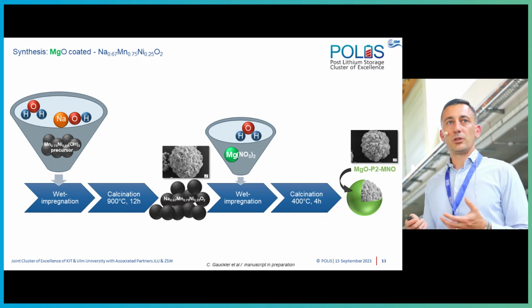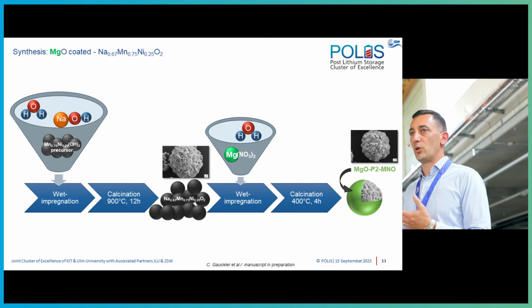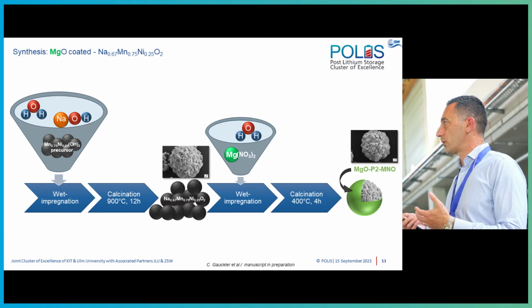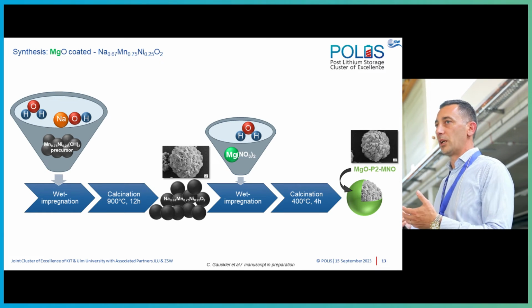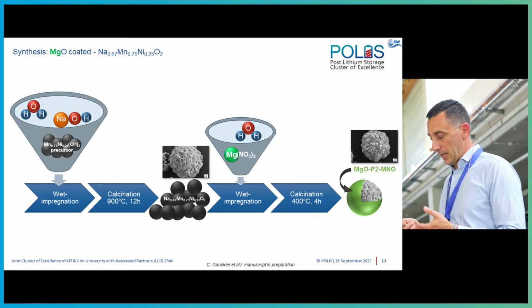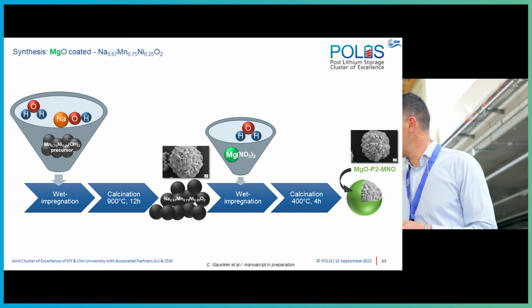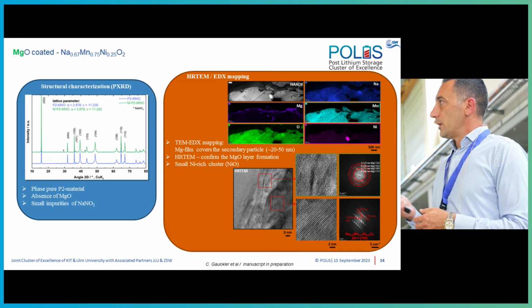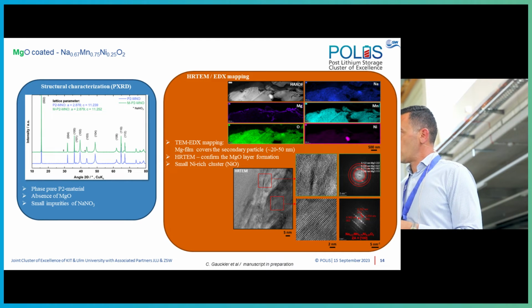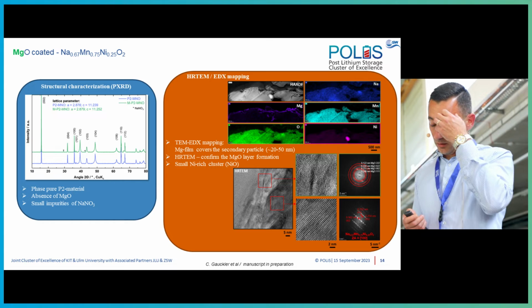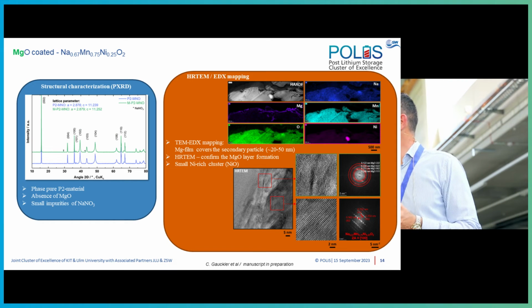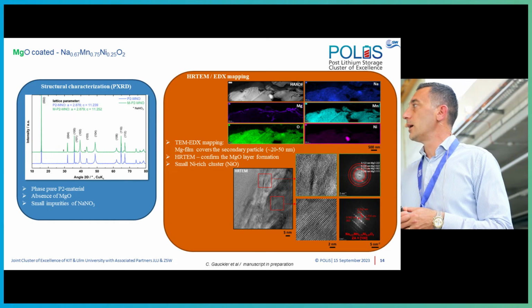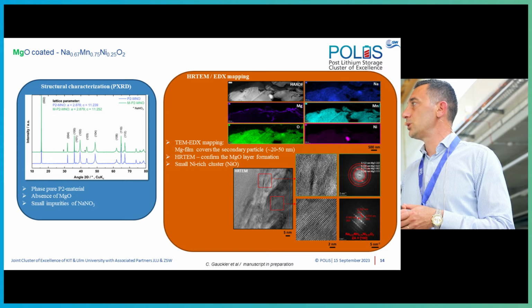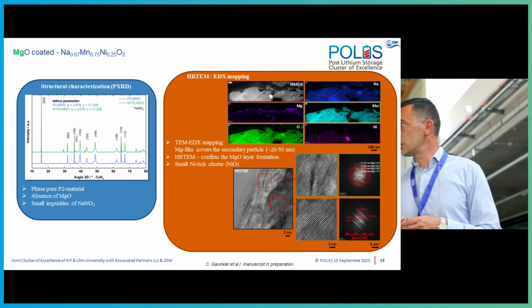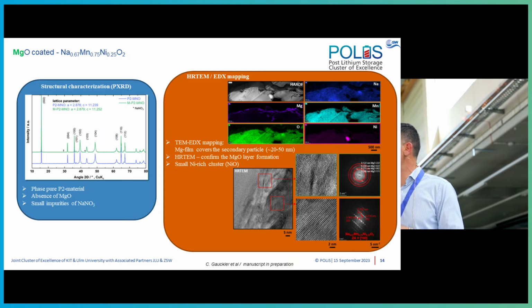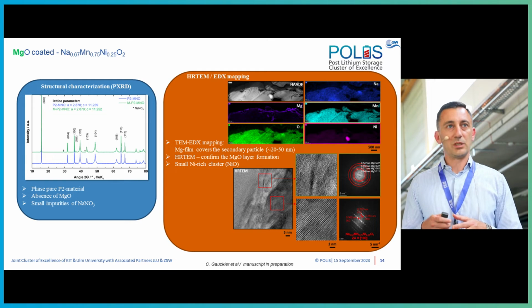We limited the temperature in order to prevent any doping in the bulk. Yeah? So we thought, okay, 400 degrees is not going to be enough to have doping, but we will have the magnesium oxide coating. And well, when we looked at the X-ray diffraction pattern of the two materials, again, both of them were phase pure P2 materials, only small impurities of sodium nitrate in the surface-coated material.